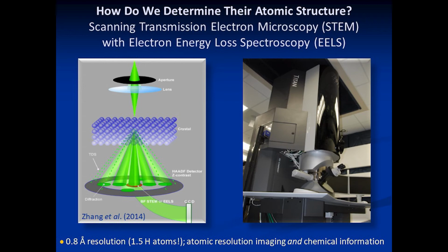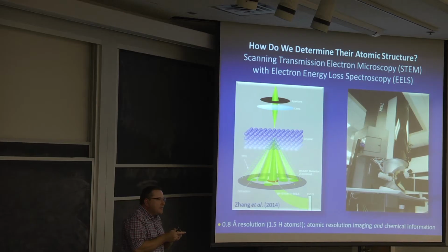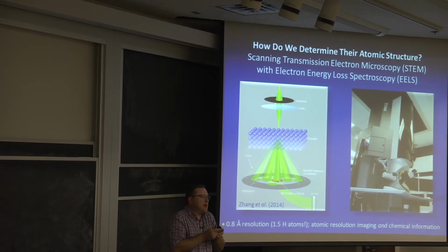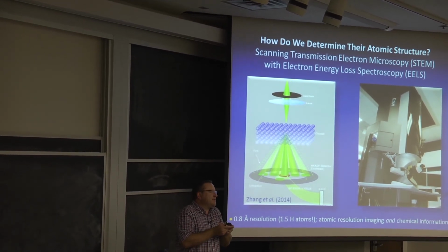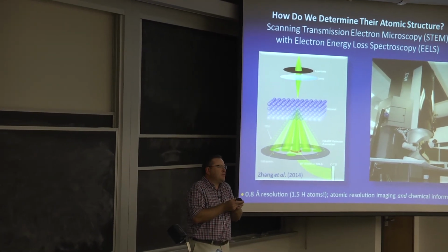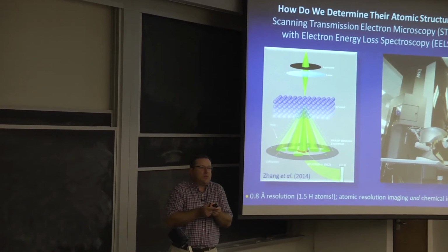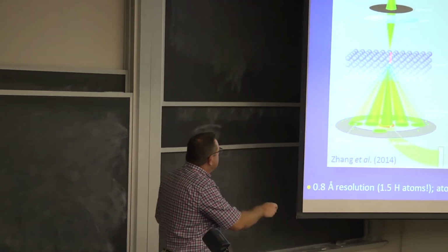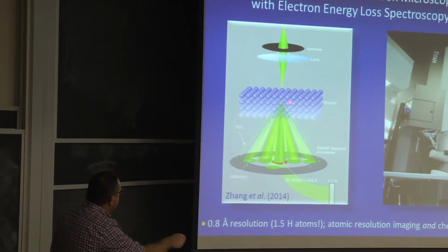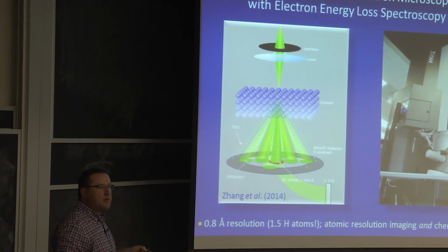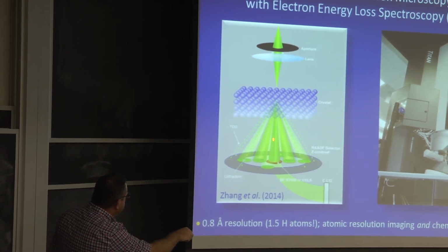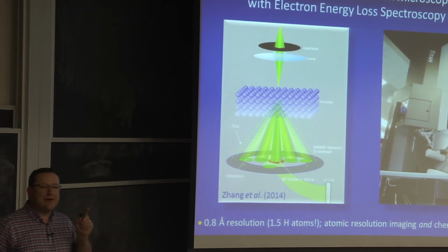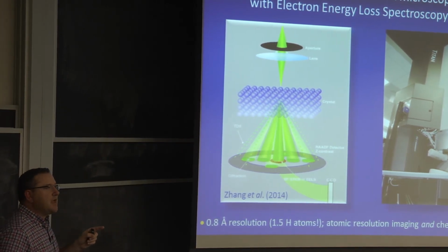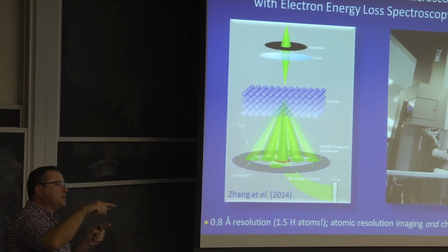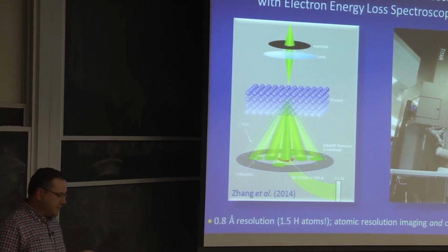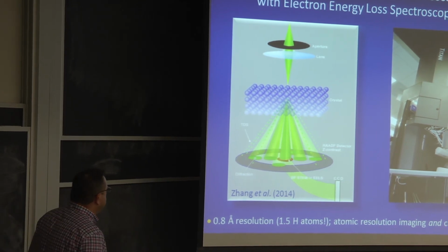And what does it do? It basically makes a very, very tiny beam of electrons. The beam of electrons is less than an angstrom wide, right? Think about that. That's ridiculous, right? A hydrogen atom is 0.53 angstrom Bohr radius. This goes down to less than the width of 2 hydrogen atoms. It fires it into a thin part of your sample. You measure the electrons that come out at really wide angles, and you scan the beam around and you make a picture. And then while you're at it, the electrons that fly through the middle, you put them into a spectrometer and you identify chemically what they went through. So you can pick out single atomic columns, and you can also know exactly what chemistry is involved in that particular column. And this is a game-changing thing in material science.